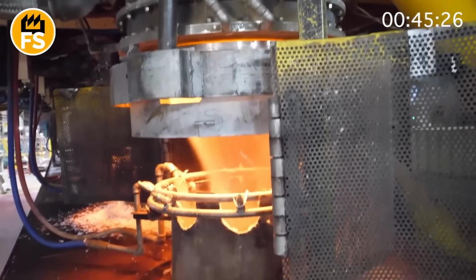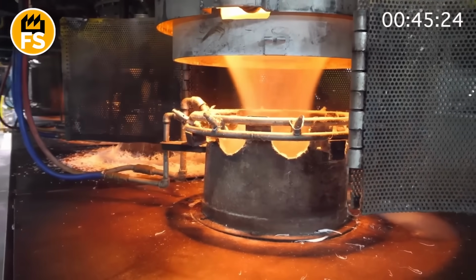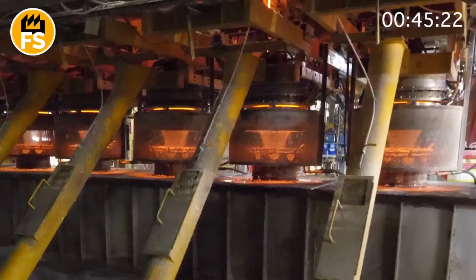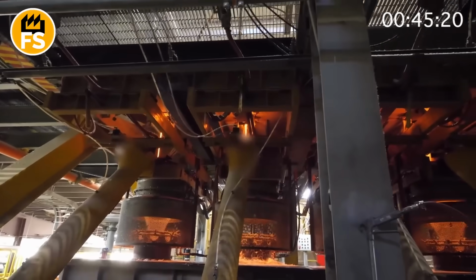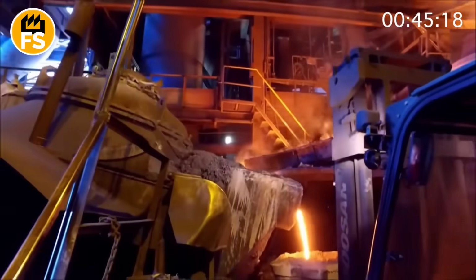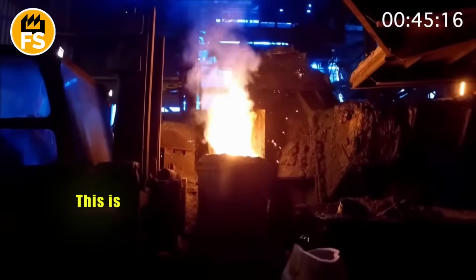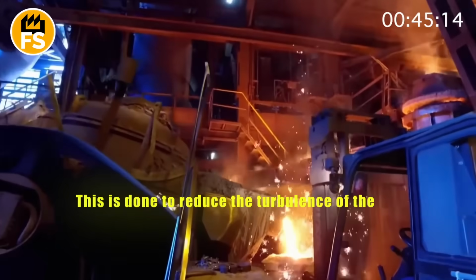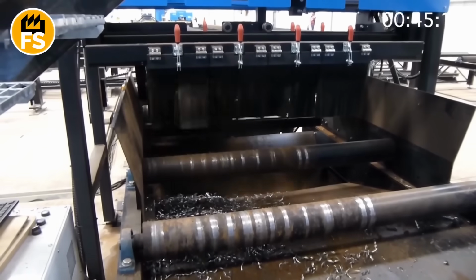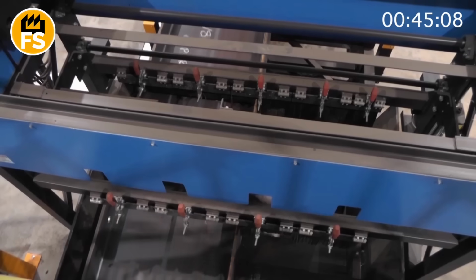From here, the stage of shape creation begins. The ladle is moved over a row of cylindrical graphite molds. A bottom pouring method is used. The metal is fed into the molds from below through a system of channels. This is done to reduce the turbulence of the flow and prevent slag and other impurities from entering the casting, ensuring maximum purity of the future wheel.